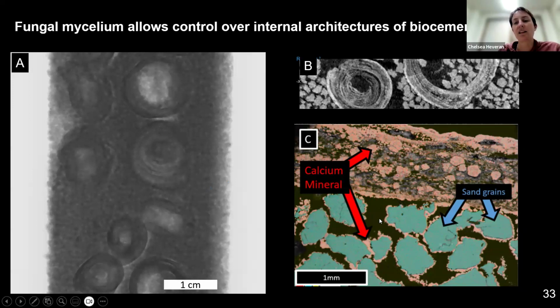But you can see here on image C, we've got sand grains. You can see what biocementation looks like through the sand grains. You have these little bridges that are incomplete, but you have much bigger calcium biominerals that are accumulating within, in this case, a little ring of that fungal scaffold that forms the osteon, those concentric rings. So we see that with this pink calcium biomineral here.